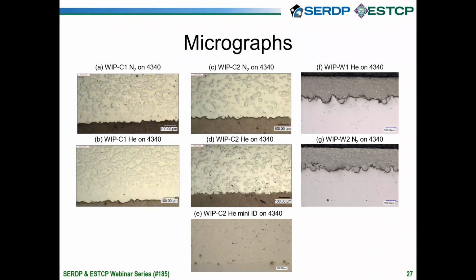With the WIP W1 and W2 coatings, you can still make out 2 distinct phases, but the characteristic size of the phases is smaller because those phases were agglomerated within a single powder particle. So what we found in general is that W1 and W2 coatings are slightly more robust than the C1 and C2 coatings because we think the coatings are more homogeneous. But there is a slight increase in cost from the W1 and W2 feedstocks because of the additional steps in the manufacturing process.